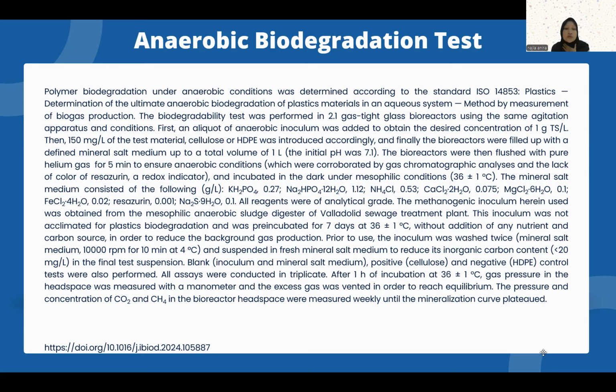In order to reduce the background gas production, prior to use, the inoculum was washed twice with mineral salt medium at 10,000 rpm for 10 minutes at 4 degrees Celsius, and suspended in fresh mineral salt medium to reduce its inorganic carbon content to less than 20 milligrams per liter.